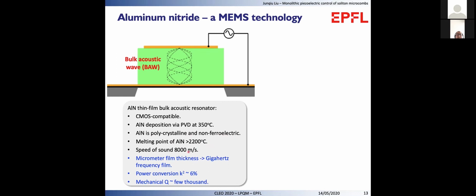The speed of sound in aluminum nitride is about 8,000 meters per second. Therefore, if you have a micrometer film thickness, you can get a gigahertz acoustic frequency. The power conversion efficiency from electric to acoustic is about 6% at a typical mechanical Q value of a few thousands.